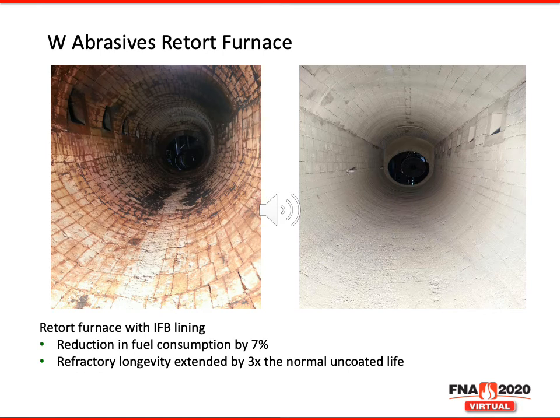At W. Abrasives in Ontario, Canada, a blasting media manufacturer, they utilize a retort furnace with an IFB, or insulating fire brick lining. Ceramic coatings were installed at approximately 3/16 of an inch to the hot face of the IFB lining. After the installation of the coatings, a reduction in fuel consumption by 7% was realized. Additionally, refractory longevity was extended by 3 times the normal uncoated life, thus greatly reducing their high costs of refractory maintenance.